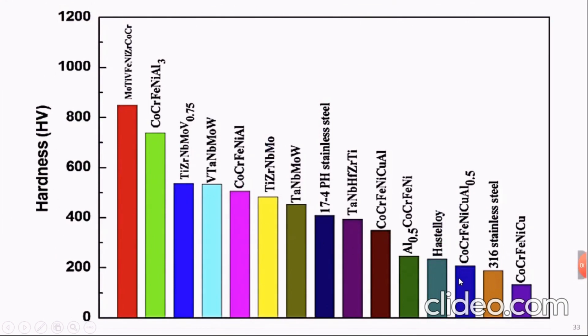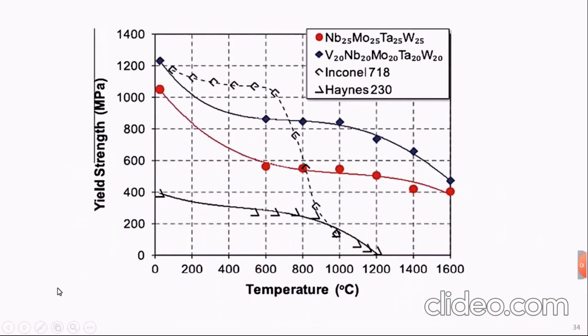If you compare the hardness of high entropy alloys to the Hastelloys, superalloys, and steel, you can find that high entropy alloys acquire the highest hardness among the other alloys. And of course, hardness is related to strength. That means these alloys also have high strength. Another important thing is the strength at high temperatures, which is very important for some applications like the aviation industry and so on. If you compare here the yield strength at different temperatures for two high entropy alloys to the superalloys Inconel and Haynes, we can find that high entropy alloys can extend their strength and keep their strength to higher temperatures. So it's very good, as I told you, in high temperature applications.